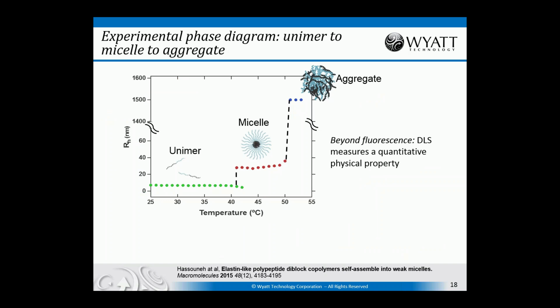Here's an example of utilizing dynamic light scattering to track the phase diagram of micelle formation. It started out as a unimer at low temperatures with a size on the order of 8 or 9 nanometers in radius. You can see this very sharp transition right around 41C. Right at 41 or 42C, you can see an equilibrium between monomers and micelles, so both of them are present and both are detected. Then at a little higher temperature, all of the monomers are incorporated into micelles. And finally, once you get to about 50C, we see this massive change in size up to greater than 1,500 nanometers associated with aggregation.